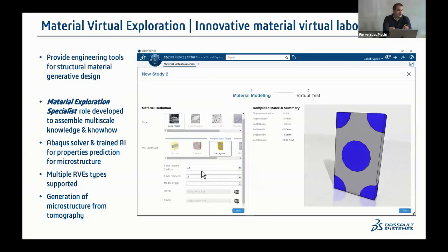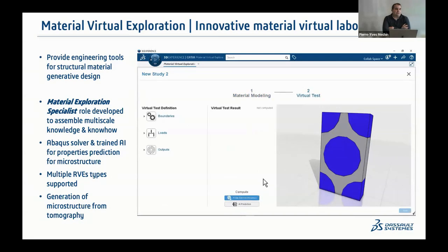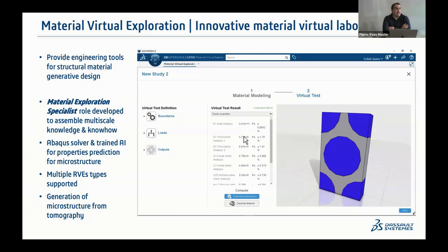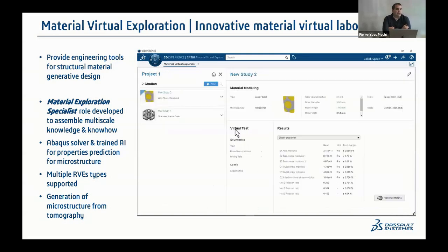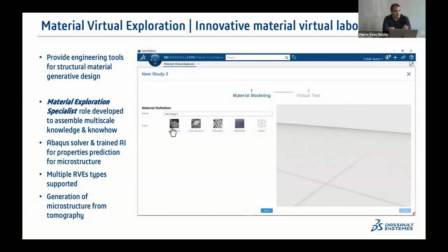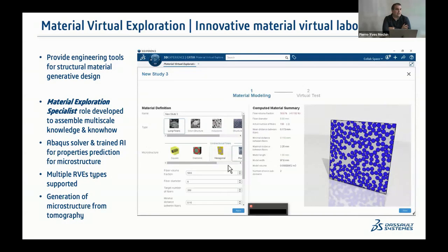We've used an AI model trained on RVE models to reduce the time of prediction, because an FE solver usually takes around 1 to 3 minutes, depending on the accuracy of the mesh. But for the inference of the AI model, it's an immediate prediction. The value of this is that we can then compute a large amount of different model configurations, where we can get an understanding of the variability of the properties.